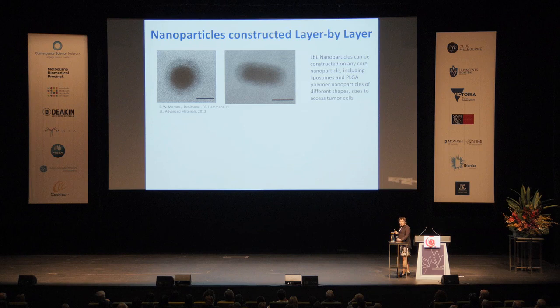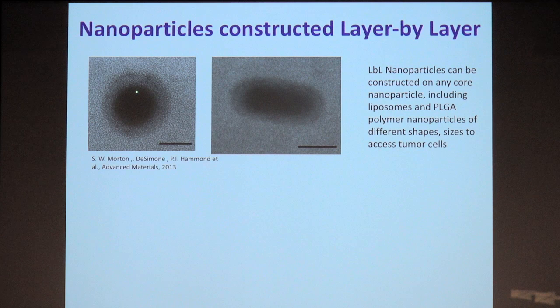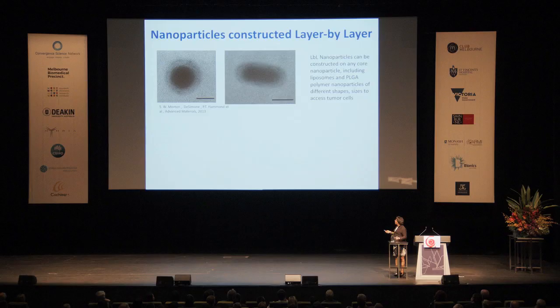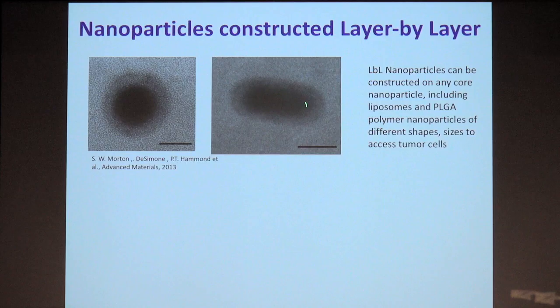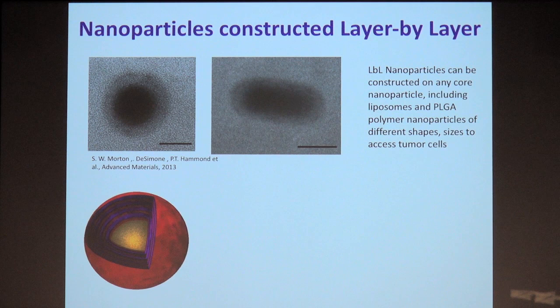Now, this is what that looks like. Here you can see a very simple polystyrene latex particle that has been coated with our layer-by-layer film, and it looks like a halo. You can't see the different layers differentiated because they all have very similar content. So in the electron microscope, they all look the same. So you see this kind of translucent halo. We can coat particles of any kind of shape or size. Here you can see an oblong particle. And we can put down as many layers as we want.